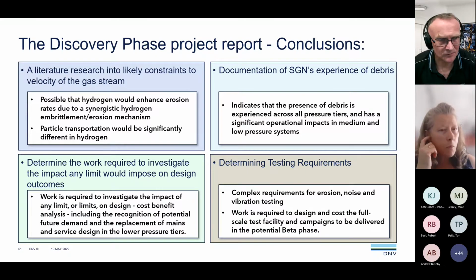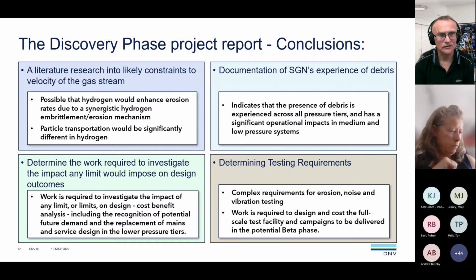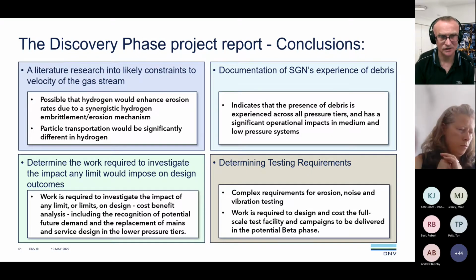So what do we find? We found a lot of quite interesting things. The literature search indicated two aspects which may well become important. It appears possible that erosion in hydrogen is different to that in natural gas, in that you may well be able to get enhanced erosion rates due to synergism between hydrogen embrittlement and particulate erosion. There are relatively few papers that indicate there may well be something in that. The other thing it showed is that moving the debris, particle transportation, would be significantly different in hydrogen to natural gas. Possibly wouldn't be able to shift as much.